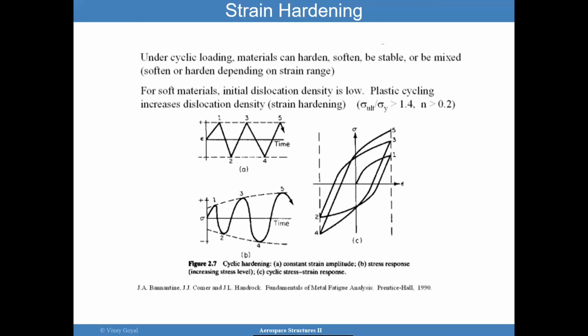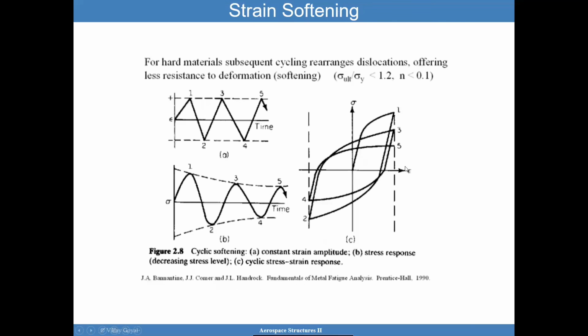So here you have a situation in A where you have a constant strain amplitude. The stress response here is increasing over time, and this is your cyclic stress strain response, okay? So this we call cyclic hardening in this situation. Notice how, as the number of cycles progress, this stress is increasing. We call this cyclic hardening.